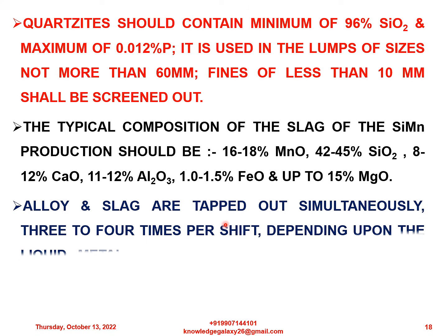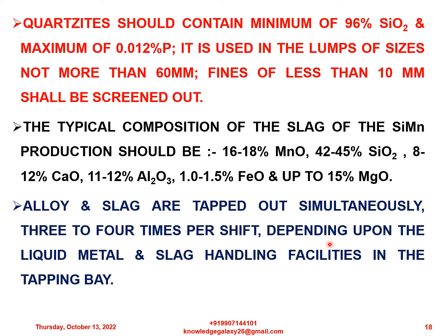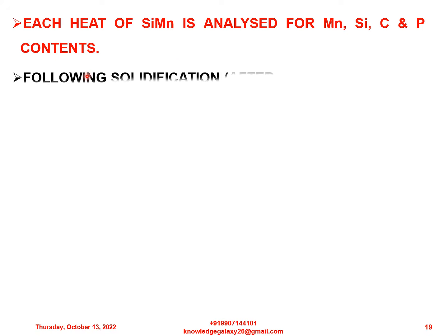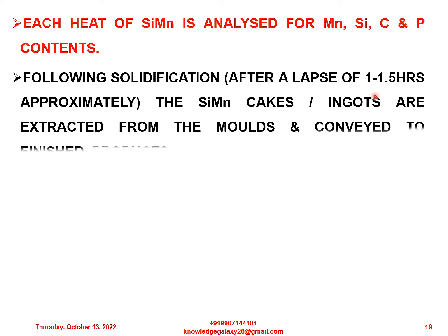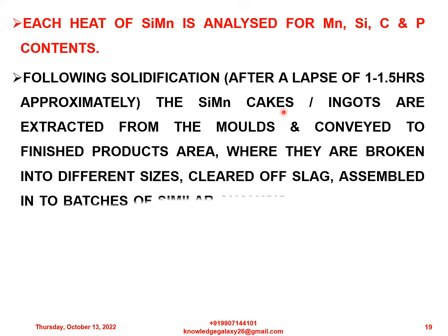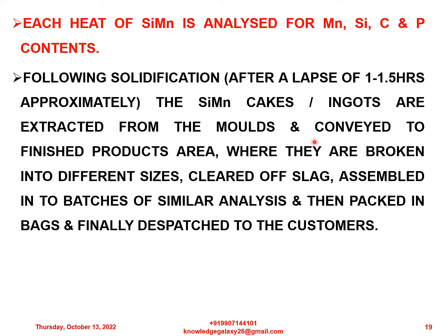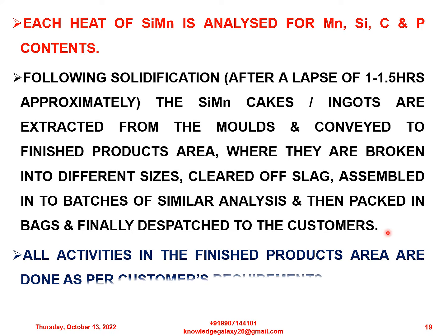Moving on, alloy and slag are tapped out simultaneously 3 to 4 times per shift depending upon the liquid metal and slag handling facilities in the tapping bay. Each heat of silicomanganese is analyzed for manganese, silicon, carbon and phosphorus contents. Following solidification after a lapse of 1 to 1.5 hours approximately, the silicomanganese cakes or ingots are extracted from the molds and conveyed to the finished products area, where they are broken into different sizes, cleared of slag, assembled into batches of similar analysis and then packed in bags and finally dispatched to the customers. All activities in the finished products area are done as per customers' requirements.